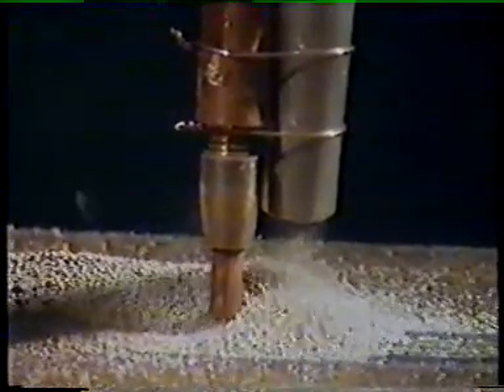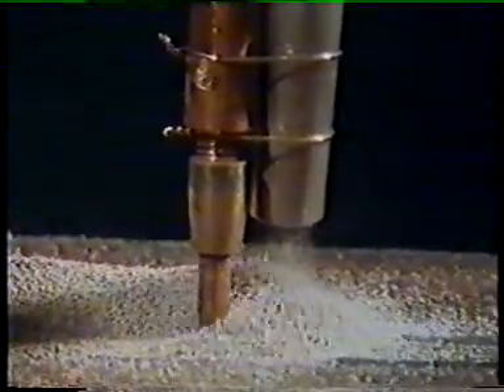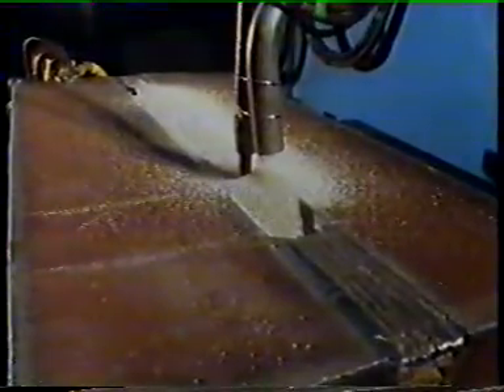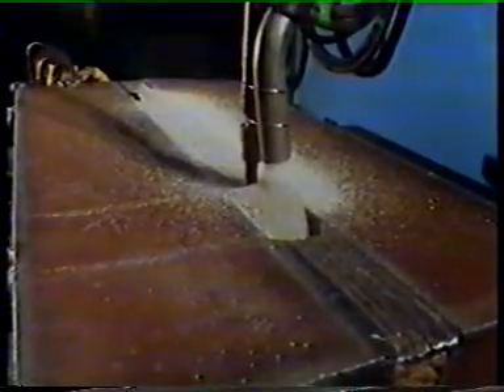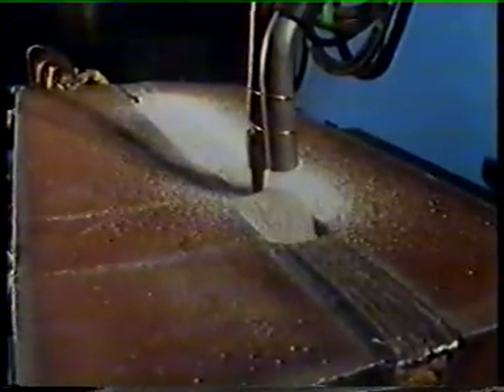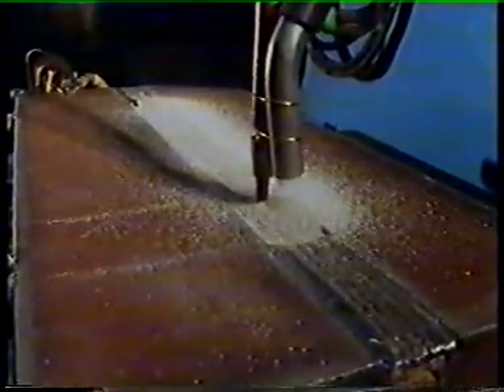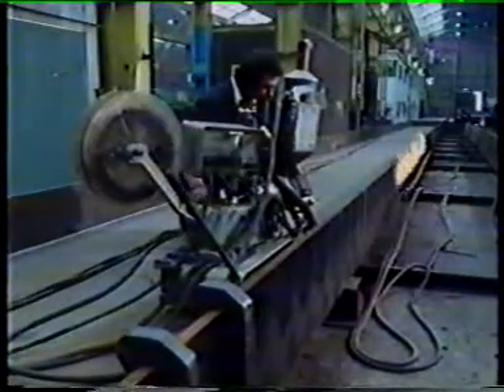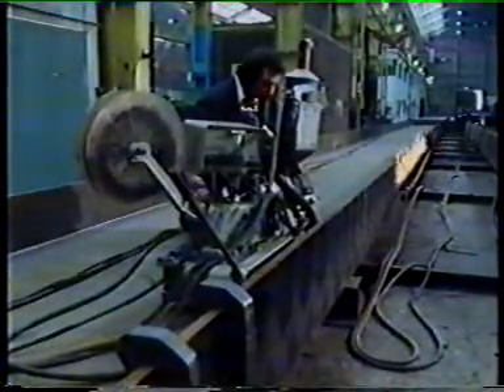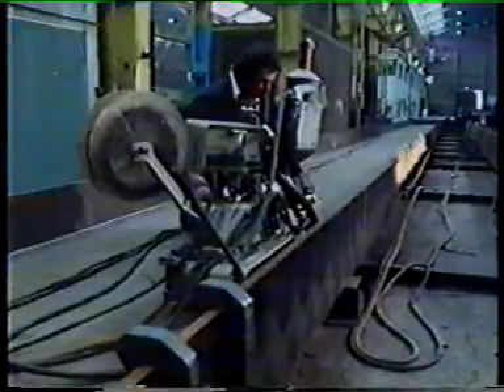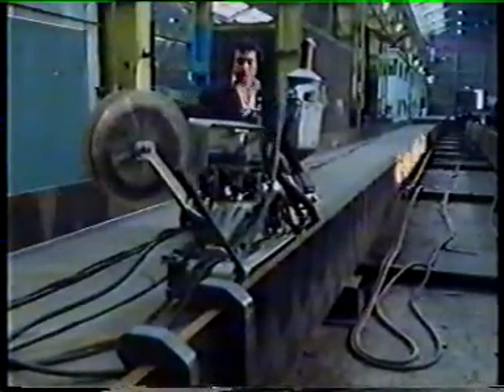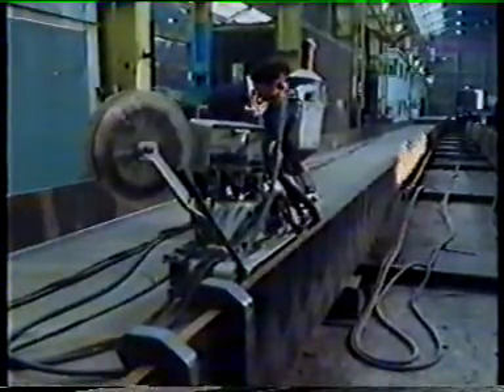Because it has a good shielding system and is automated, high currents between 500 and 1,000 amps can be used. This makes submerged arc an ideal way to weld heavy materials. That's why it's found in most fabricating and welding shops. Because it's easy to weld long joints, large components, like this 20-ton girder for a bridge, are ideally suited to submerged arc welding.